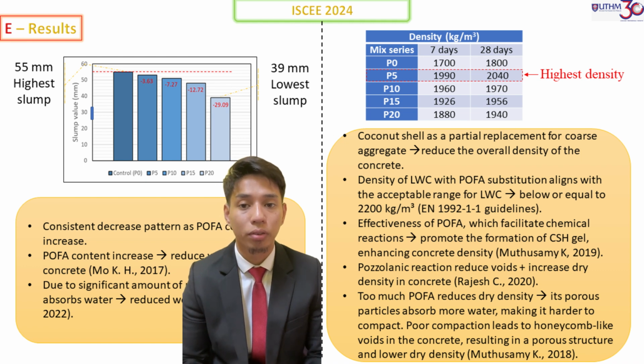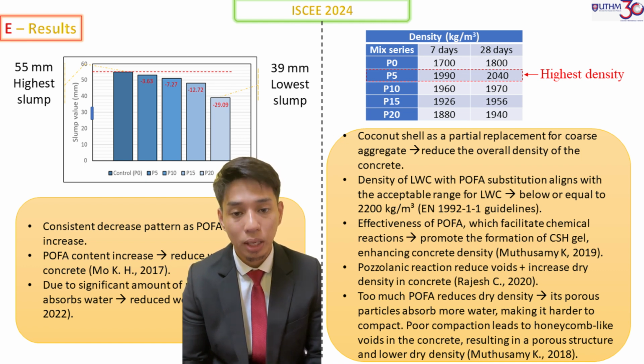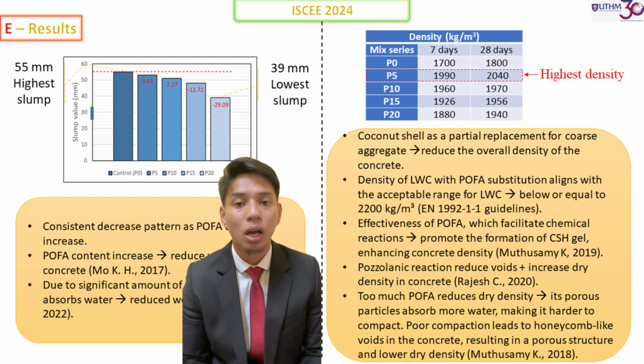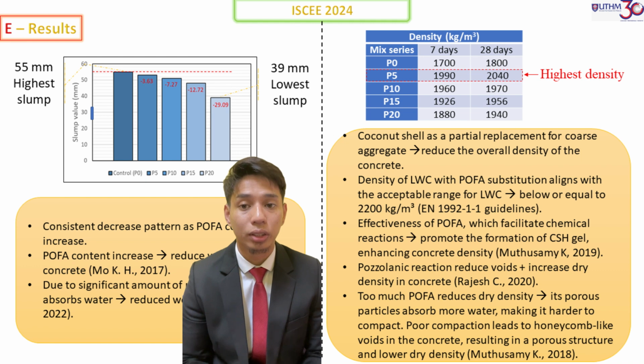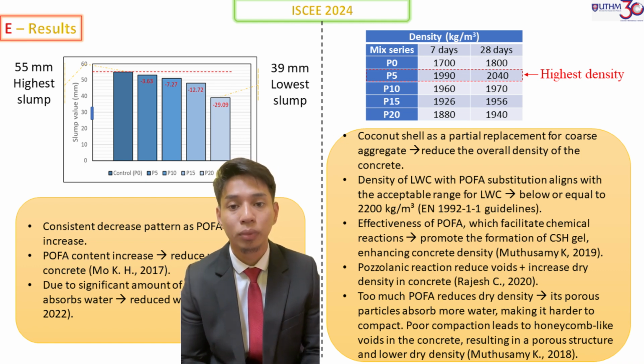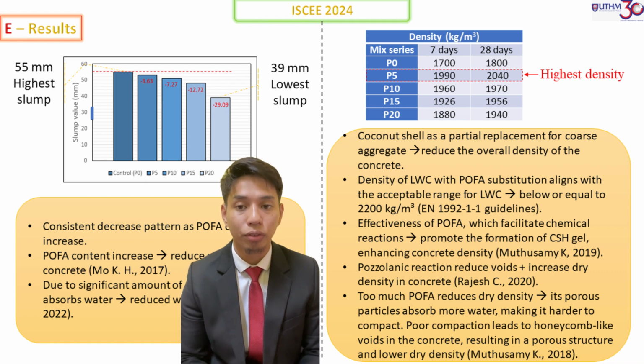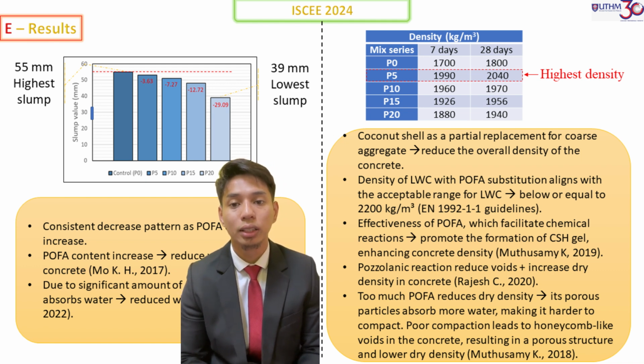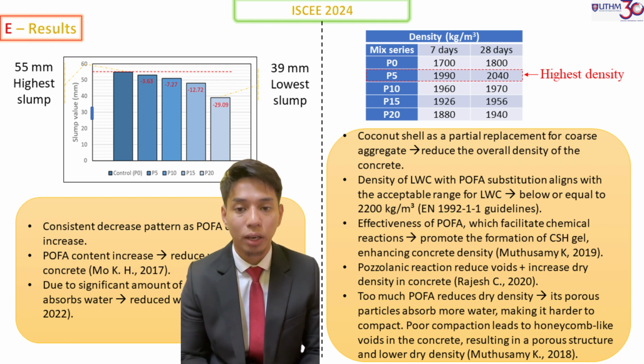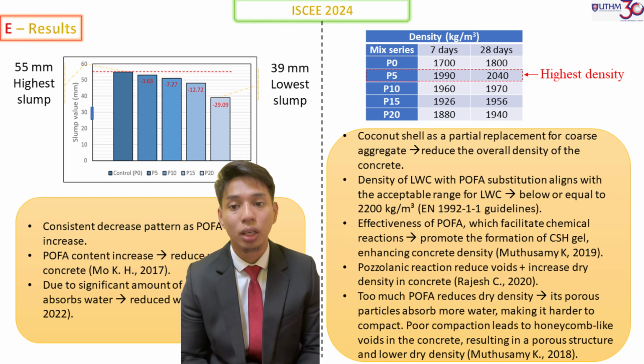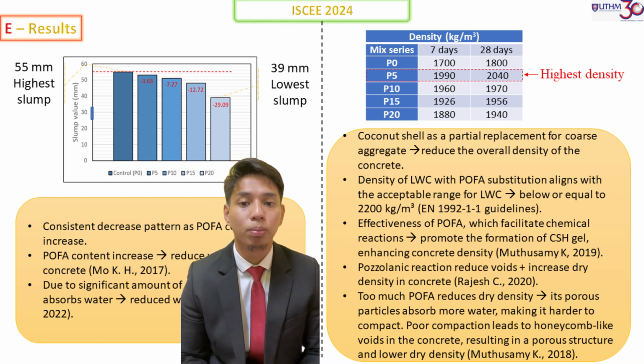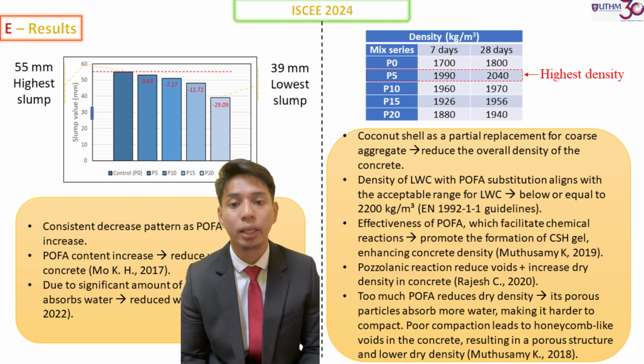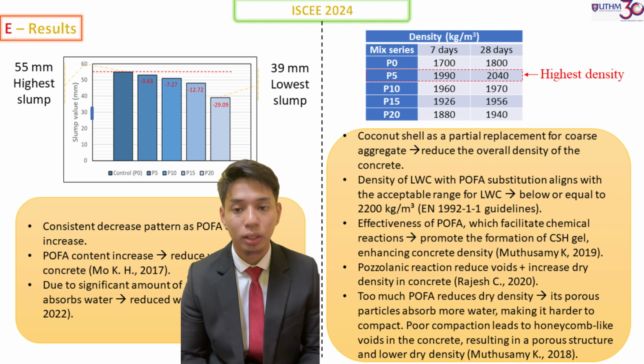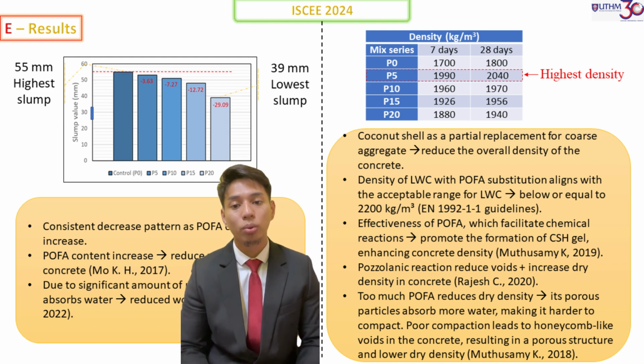The effectiveness of POFA facilitates the chemical reaction known as pozzolanic reaction, which promotes the formation of calcium silicate hydrate gel, enhancing the concrete density. So the pozzolanic reaction reduces the voids and also increases the dry density of concrete. But too much POFA will reduce the dry density because it is a porous particle that absorbs more water, making it harder to compact. And if the compaction is poor, it will lead to honeycomb-like voids in the concrete, resulting in a porous structure and lower dry density.